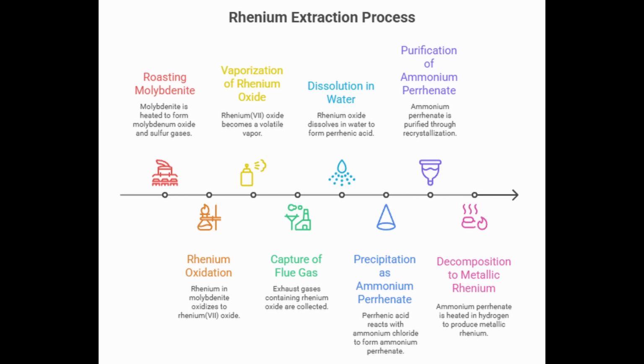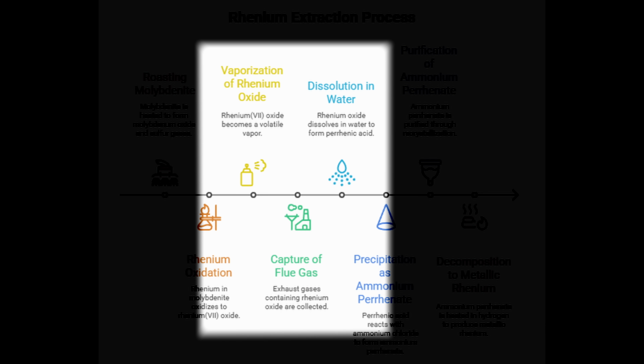In the typical process, molybdenum is extracted from copper ore as molybdenum disulfide concentrate. To get molybdenum metal, the concentrate is roasted in air, heated strongly so that it converts to molybdenum oxide and sulfur gases. During this roasting, the rhenium present in the molybdenite also oxidizes. Rhenium turns into rhenium-7 oxide, which, unlike molybdenum oxide, is volatile. The rhenium oxide becomes a vapor and exits with the exhaust gases from the roaster. This might sound like we're losing the rhenium, but in modern operations, those gases are carefully captured.